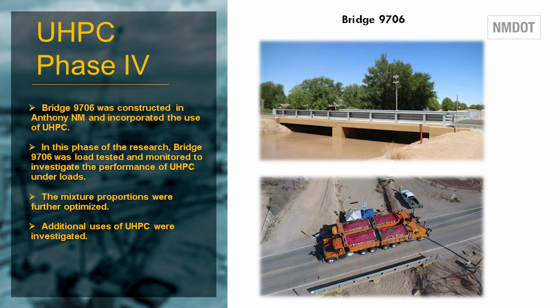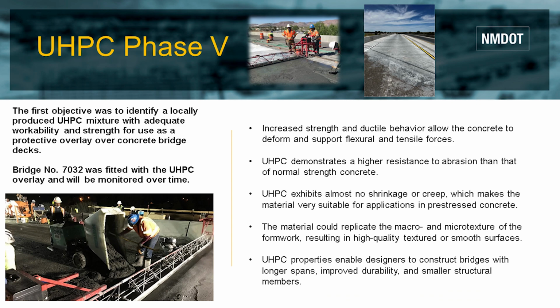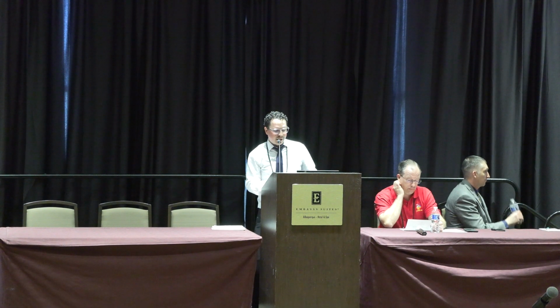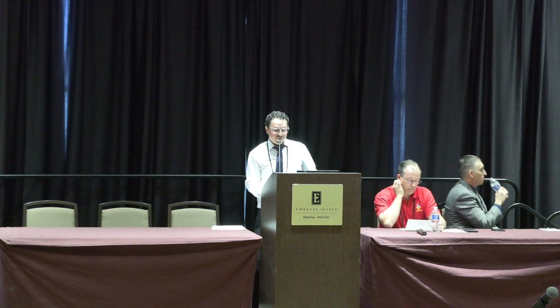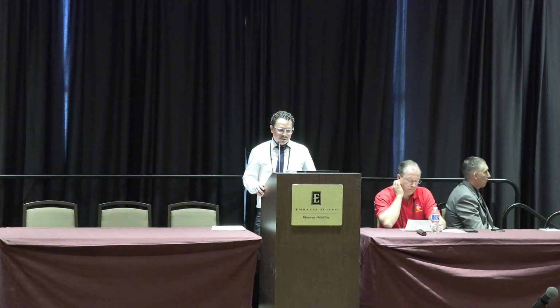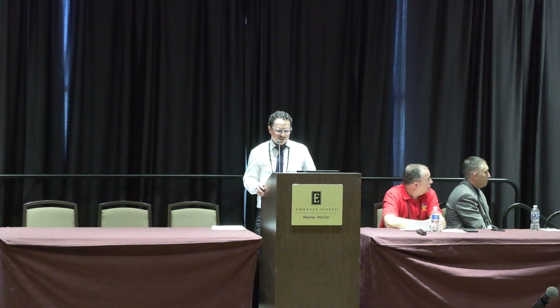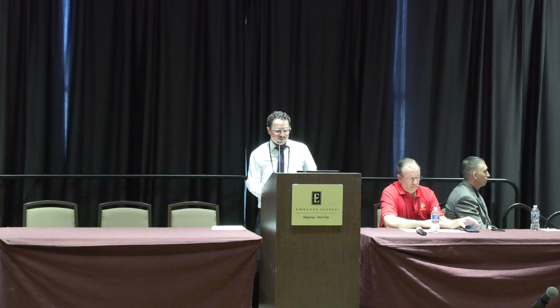And currently this project is in its 5th phase and it's still ongoing. The first objective was to identify a locally produced UHPC mixture with adequate workability and strength for use as a protective overlay over concrete bridge decks. They chose bridge number 7032, and that's in Socorro, and it was fitted with the UHPC overlay and will continue to be monitored. The test results would establish an experimental background and would be used to verify analytical procedures and develop design tools and recommendations for implementation of this material.